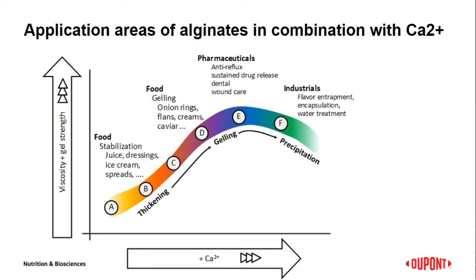Alginates are used in a variety of different application areas. These take advantage of the strong interaction of alginates with calcium ions. Low amounts of calcium will only increase the viscosity of the solution, which is used for stabilization of juices, dressings, etc. As the concentration of calcium and the viscosity increase, the solution changes from pseudoplastic to thixotropic rheological behavior. Such solutions need time to recover to the original viscosity after high deformation processes. Examples for such applications are gel structures like creams or others. Further increased amounts of calcium lead to strong gels, which are used in anti-reflux formulations or for sustained drug release.